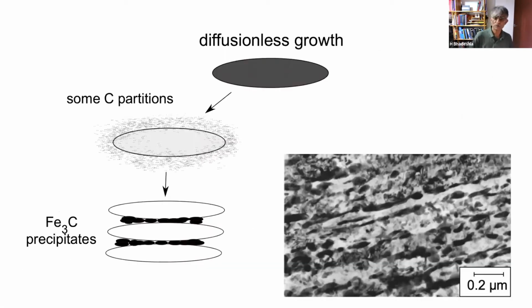Okay, so the transformation is diffusionless, but at the temperatures where bainite forms, the carbon escapes into a place where it's more comfortable and eventually precipitates as cementite. Now, if you're designing a strong steel, then cementite is not a good thing to have because it's a relatively hard phase and it will nucleate cleavage cracks. Okay, so we want to stop the reaction here. And you can do that by adding silicon. Now, it's been known for at least a century that in cast iron, when you add silicon, instead of getting cementite, you get graphite.